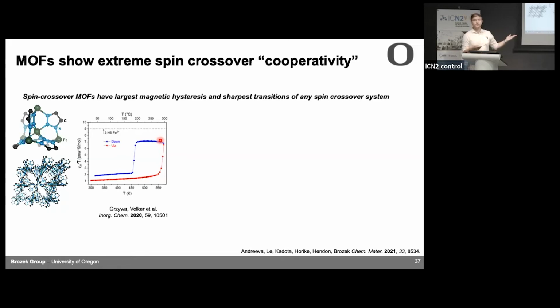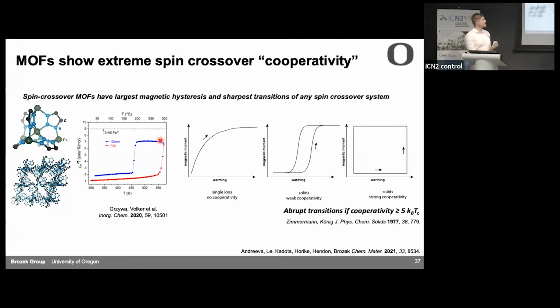It's not clear why. We thought maybe dynamic metal ligand bonds have something to do with this really bizarre spin crossover behavior. By the way, this is really different from molecular spin crossover systems, where if you heat them, the magnetic moment just gradually increases. Most materials, you get much smaller hysteresis windows. And in the 70s, theoretical physicists predicted that you would get this perfect box-like relationship if you had lots of cooperativity, whatever cooperativity means. That was another thing that was a mystery to me.